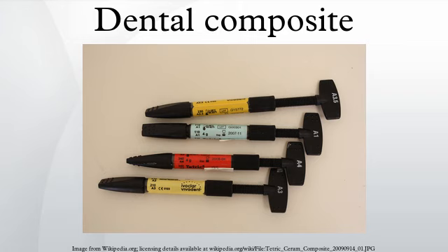The DeMarco review found that the main reasons cited for failure of posterior composite restorations are secondary caries, fracture, and patient behavior, notably bruxism. Causes of failure for amalgam restorations reported in the Manhart et al. review also include secondary caries, fracture, as well as cervical overhang and marginal ditching.